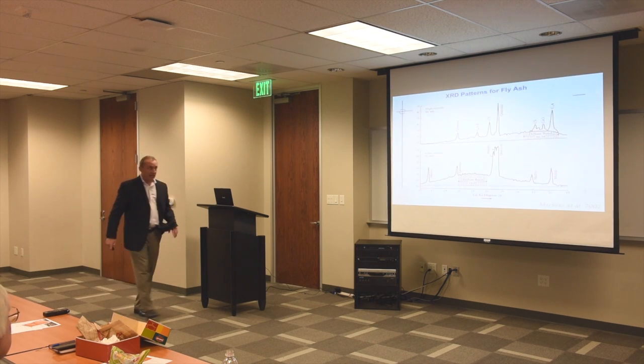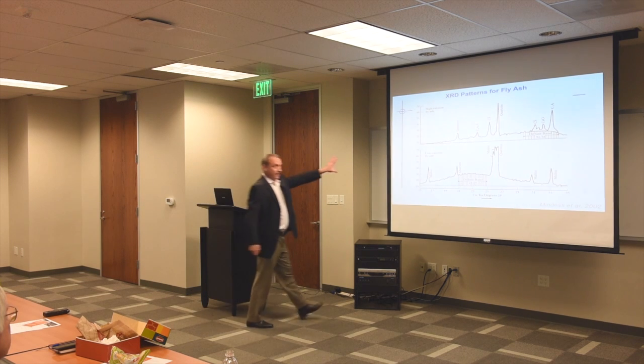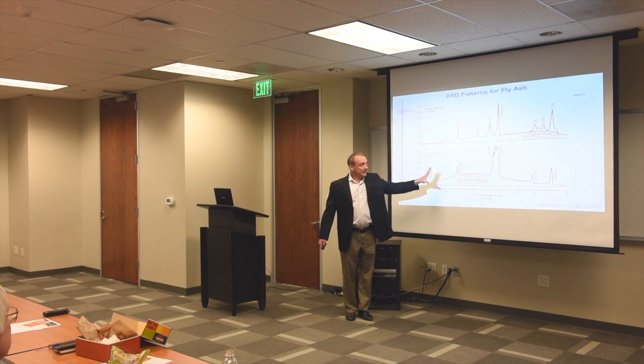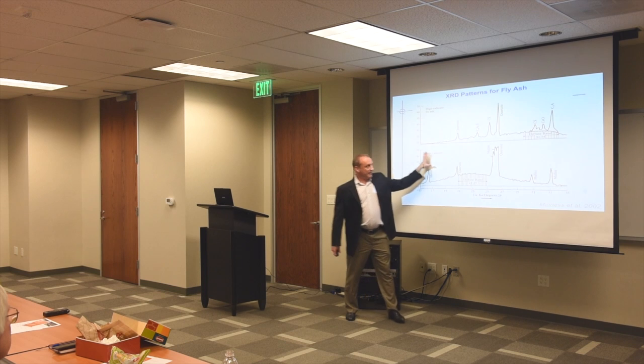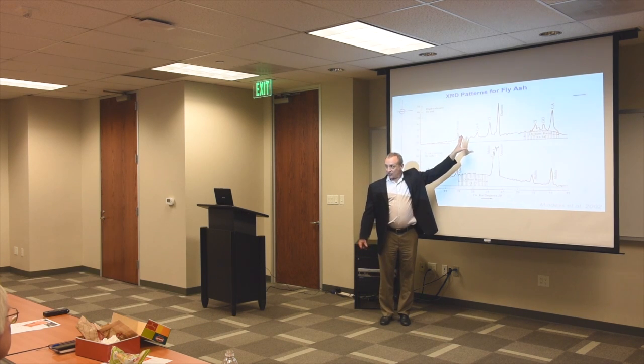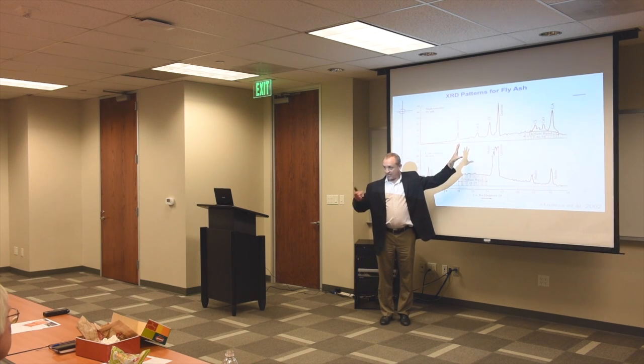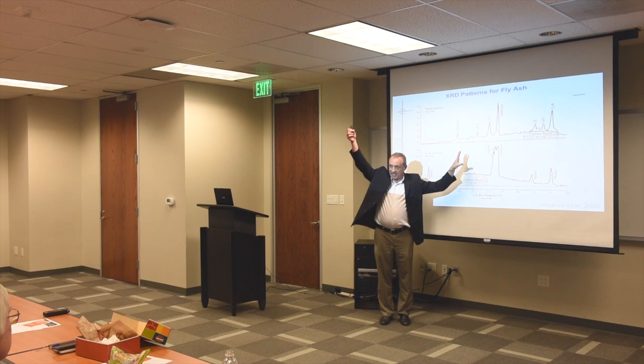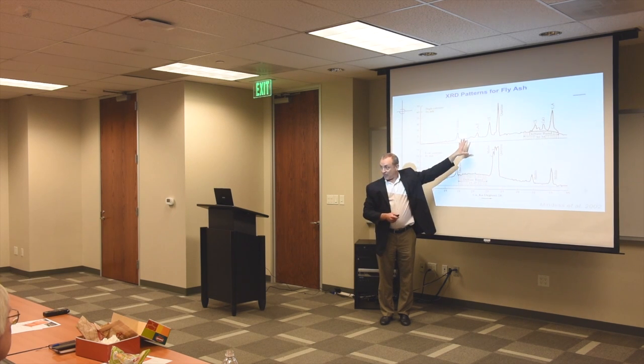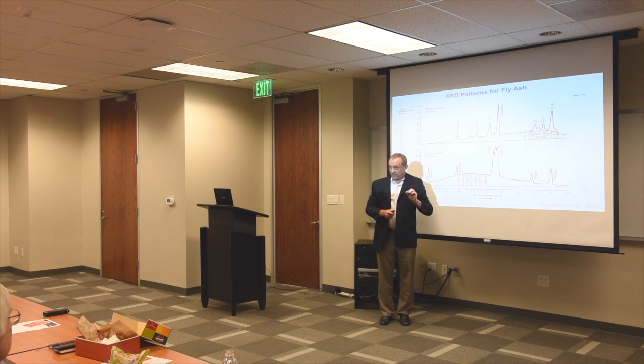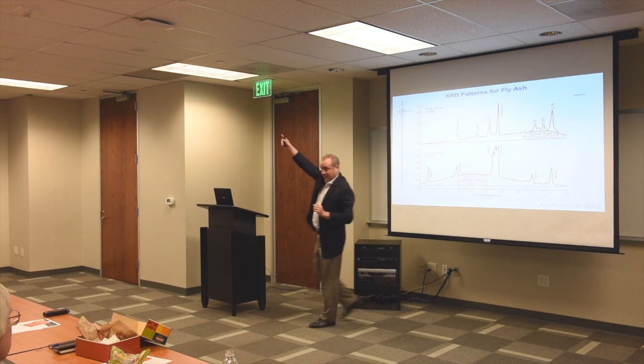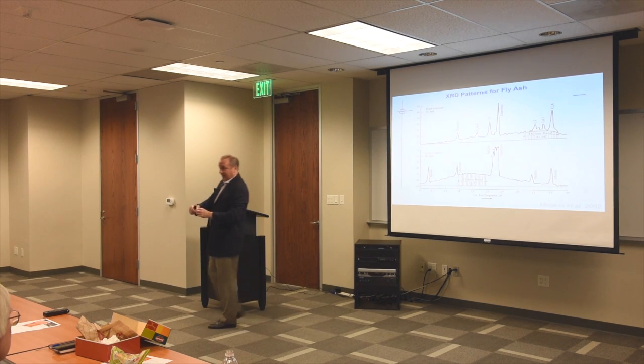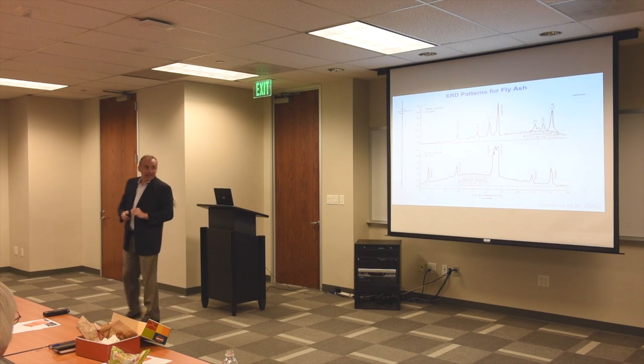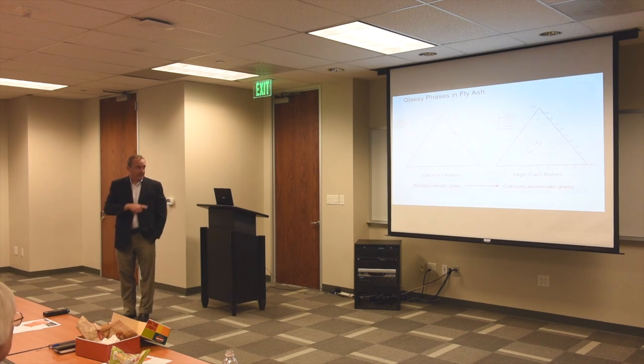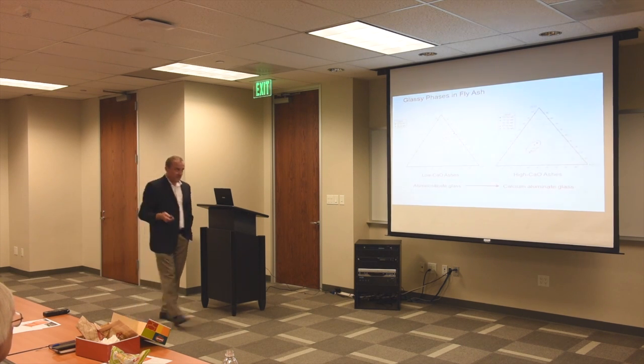It will change in a way where the crystalline aspects of it change drastically. You'll notice - I'm not going to get into all the details here - but we actually sequester the sulfates, or the SOX, that would otherwise go up the stacks. We make them precipitate out in the ash. The good news is it's not going up the stacks as emissions. The bad news is it's staying in our fly ash. And it also affects the glassy phases.